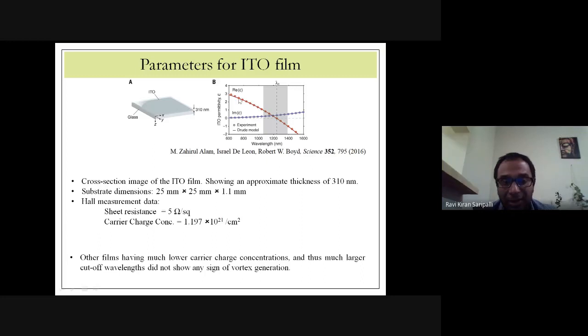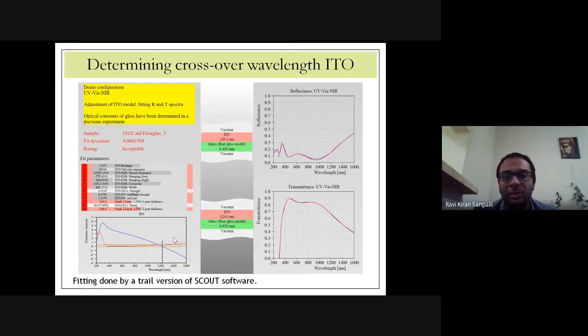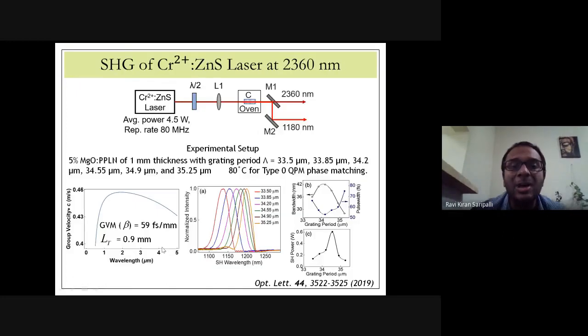And this leads to a cutoff wavelength of about 1240 nanometers. And now we have this film, so we also characterized it. We did a Drude fitting to the reflectivity and transmittivity, and saw that the cutoff is about 1240 nanometers, where the real part of epsilon goes to 0. And now you want to generate this wavelength in the lab. So we did a second harmonic generation of a 2360 nanometer source, and you were able to achieve 1180.